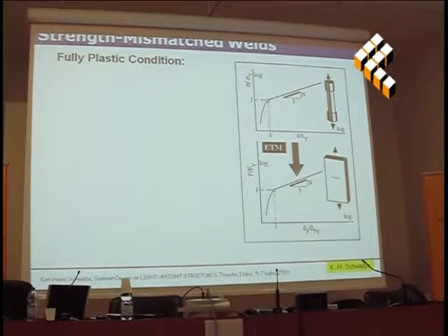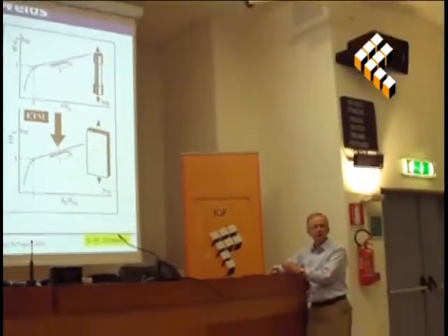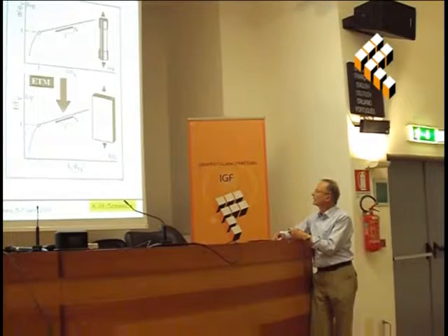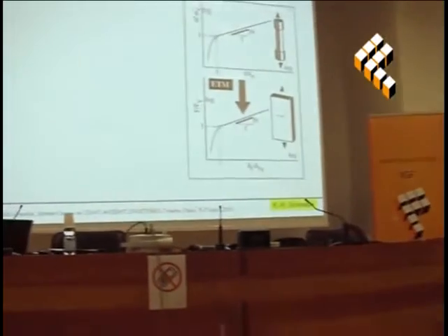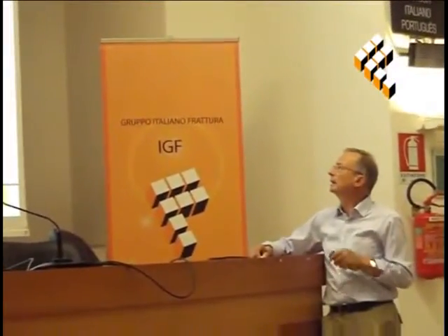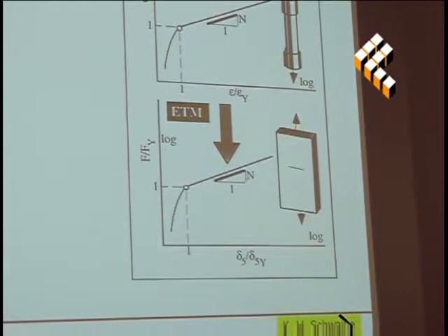We don't need finite elements. Like I said yesterday, I'm fond of simpler ideal models. So this is what is predicted to happen, and I can tell you, I've done this validation on a number of materials. I've done it myself, and I used plots of the stress-strain curve. And in the same diagram, I plotted measured delta 5 values. And at the end, you can't distinguish.